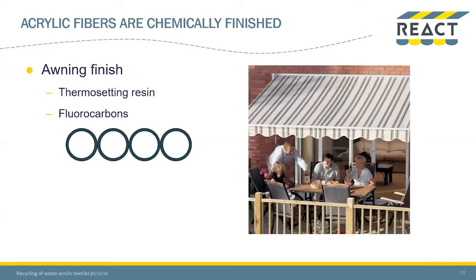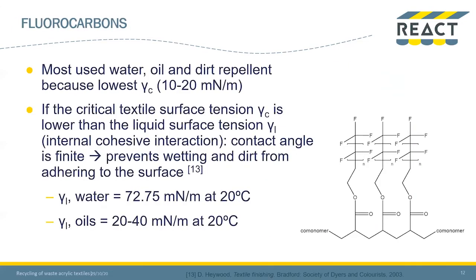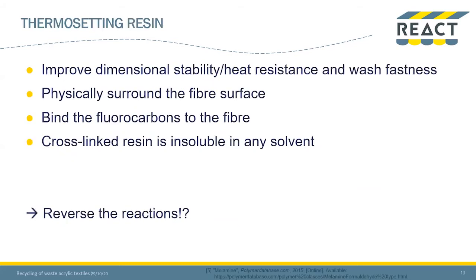So the awning finish consists of a thermosetting resin and fluorocarbon resin, which surrounds the fibers. The fluorocarbons are the most used water, oil, and dirt repellents because of their low surface tension. And the thermosetting resin improves the dimensional stability, heat resistance, and wash fastness of the fabrics. This thermosetting resin physically surrounds the fiber surface, and we believe it also binds the fluorocarbons to the fibers as well.